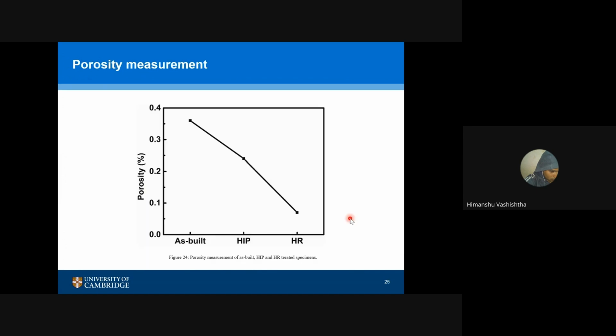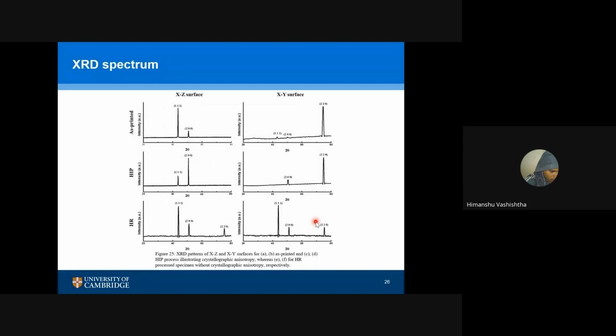So we calculated the porosity measurement using the standard Archimedes principle, using the standard density and the measured density. Then you can calculate the porosity volume fraction, percentage of porosity. The as-built has pretty high porosity percentage. When you go for hot isostatic pressing and hot rolling, it's almost close to the standard theoretical density, so very little porosity was there.